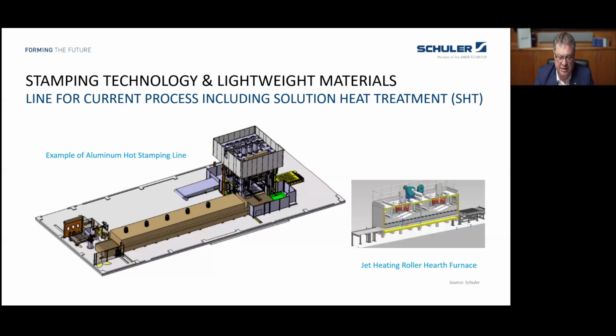So you can see on the left side a classical hot stamping line with a destacker area, then the roller hearth furnace with the jet heating on top, and then a centering station, a hydraulic press with a feeder for forming and quenching, and then at the end you have the end of line conveyor to bring the parts out of the line. So this is a normal setup for the current process for aluminum hot stamping.